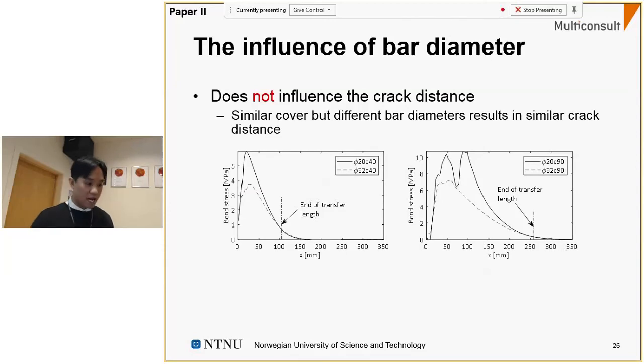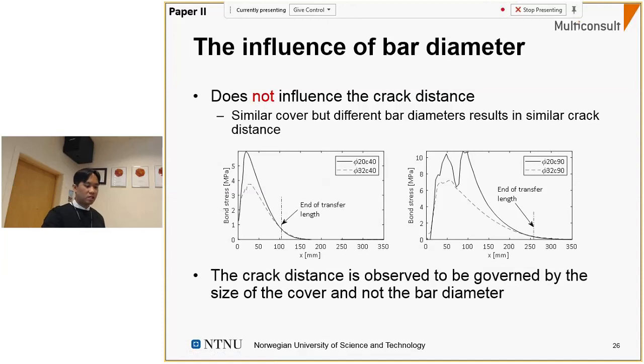And this can be proved by looking to the bond stress distribution of the RC ties here, where we see that we have now compared the bond distributions for two RC ties having the same cover but different bar diameters. And what we see here is that the bond stress distribution is pretty much affected by the bar diameter. However, the point at which the bond stresses become negligible, approximately under 1 megapascal, is at the same location over the bar length, meaning that although the bond stress distributions are not similar, the crack distance, or the distance where a crack occurs, is at the same place over a bar length. So what is observed is that the crack distance is governed by the size of the cover and not the bar diameter.